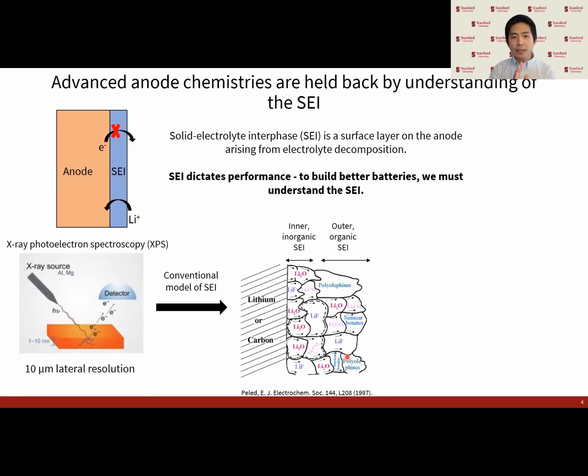But still, people have used this technique to identify the components within the SEI, mainly lithium fluorides, oxides, and carbonates, and built models of the SEI structure from XPS, which typically is thought to consist of a mosaic of these different phases. But since XPS doesn't offer any spatial resolution, the heterogeneity among these phases isn't really well understood. For example, are these grains of lithium oxide at the nanometer scale or the micron scale?